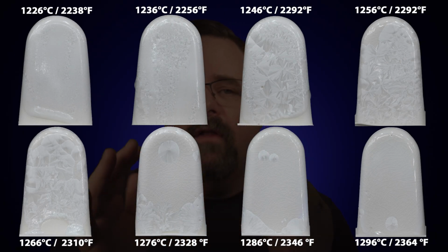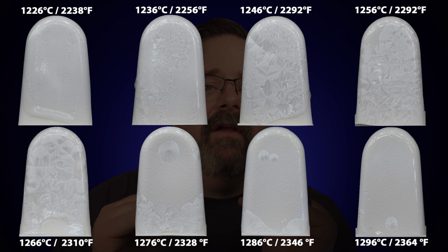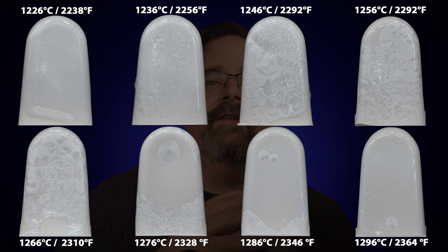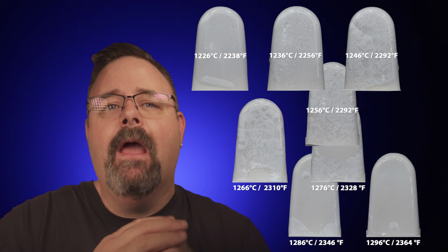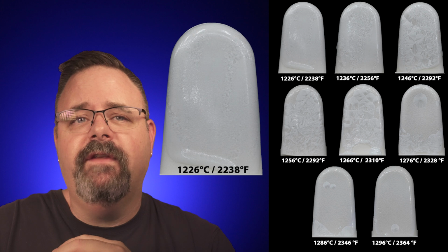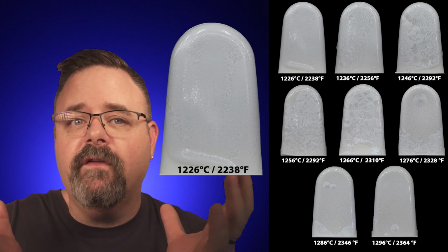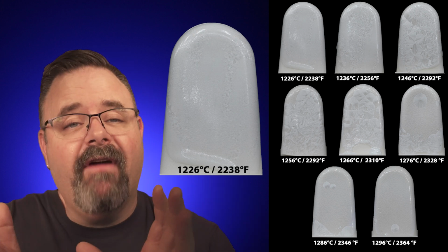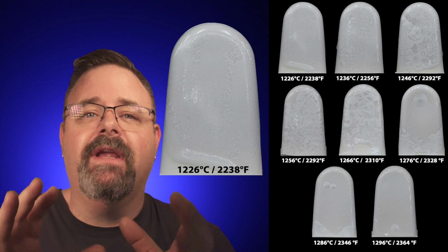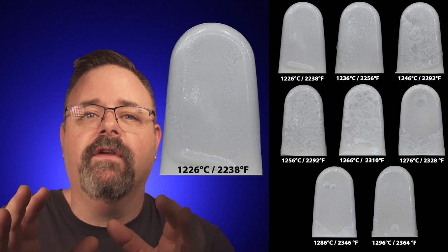Let's go back to a zinc silicate glaze here, and this is all the same glaze. I just made 8 tiles and I fired them at increasing temperatures. So we're going up in 10 degrees C, we're starting at about cone 6 and we're going to over cone 10, every 10 degrees C. Well, the version at cone 6 at 1226 here looks matte, quote unquote. It's matte via texture, but not matte via chemistry. It is an over-nucleated crystalline glaze.